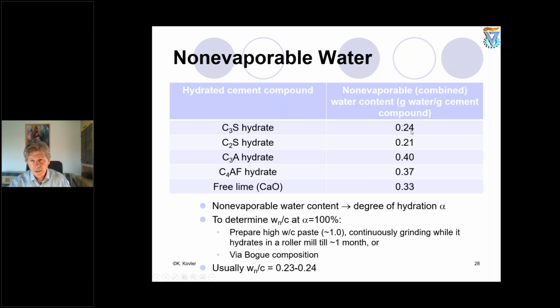Non-evaporable water, if we calculate it using, for example, stoichiometric calculations, is different for different hydrates. But in principle, if we come to the weighted average of the non-evaporable or combined water content, we are speaking about a water to cement ratio of just 0.23, 0.24 for this bound water. But this is the part of the water relative to cement which is needed to form hydrates. But unfortunately, or maybe fortunately, I don't know, we will discuss it later, this very low water cement ratio is not enough to make complete hydration of Portland cement.